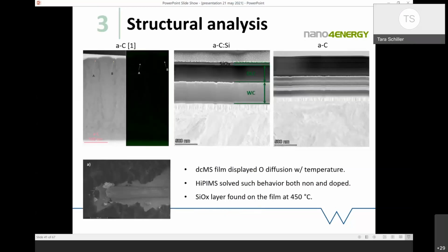So I just wanted to put up a couple of the results. One of the things that we've seen, I use the royal we here. My students are doing the work and I'm basically here presenting it on their behalf. If we've got the amorphous carbon here, if you can see these nice grey channels down here, we get this sort of effect occurring. This is, you can see here, amorphous carbon. We're looking at 500 nanometers. This one isn't quite as clear, but we can see the contrast with it. I think I probably need to reassure you it's there.